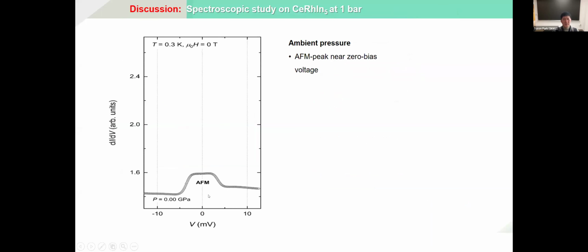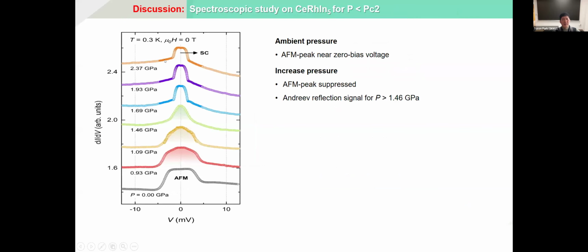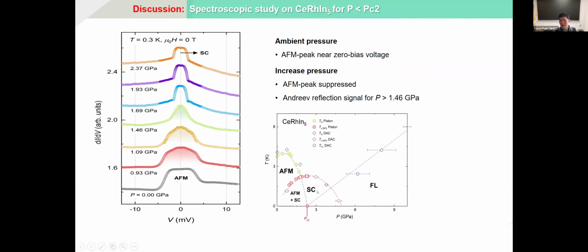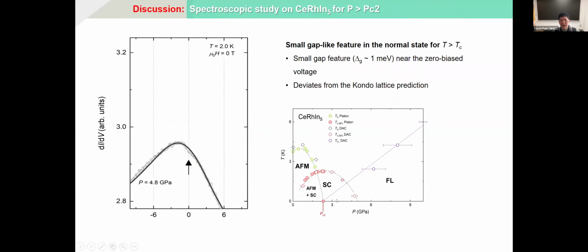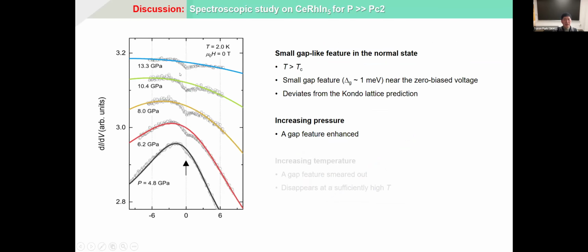And this is the differential conductance in the AFM state, and these features, the suppression of the AFM state and the appearance of a superconducting state at 0.3 Kelvin, were consistent with the previous report of this phase diagram. And then at 4.8 GPa, which is like this one, and at around 2.0 Kelvin, which is above Tc, you can see a slight dip. And then with further increasing pressure, you can see that this very nice dip develops under pressure.